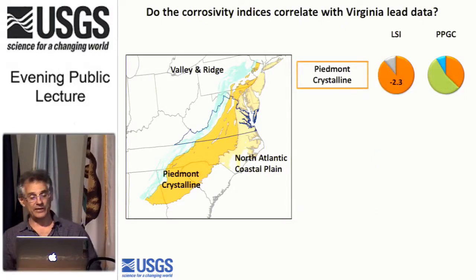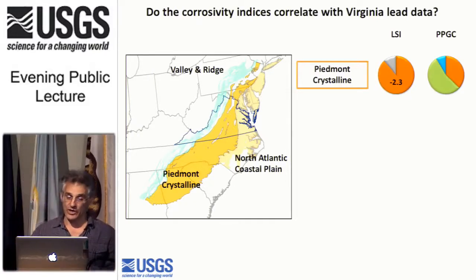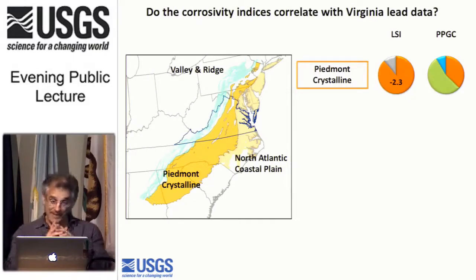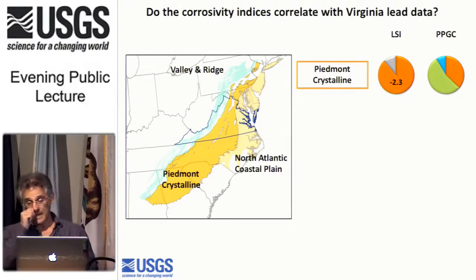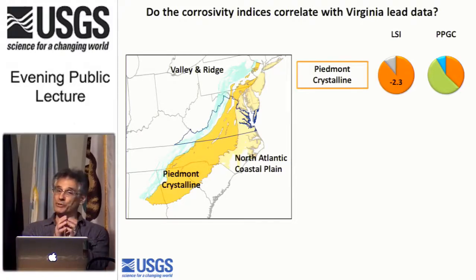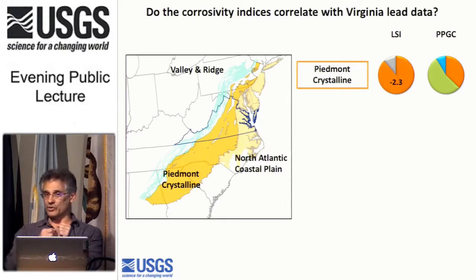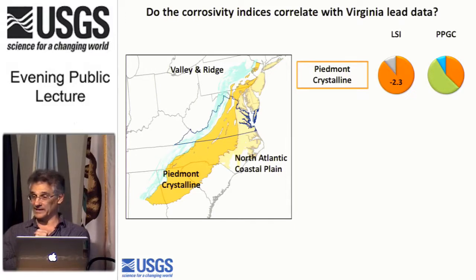So let's start with the Piedmont crystalline. I've drawn a nice orange box, tried to match those colors. That pie chart under the LSI has a number posted on it, negative 2.3. That is the average value for the Langelier saturation index for all wells in the state of Virginia in the Piedmont crystalline. And there's more than 1,000 samples here, to give you some sense of the data set. The pie chart shows what proportion of those samples are more negative than 0.5. The gray shows what proportion are indeterminate. And I don't know that there's even a blue slice in there for scaling.